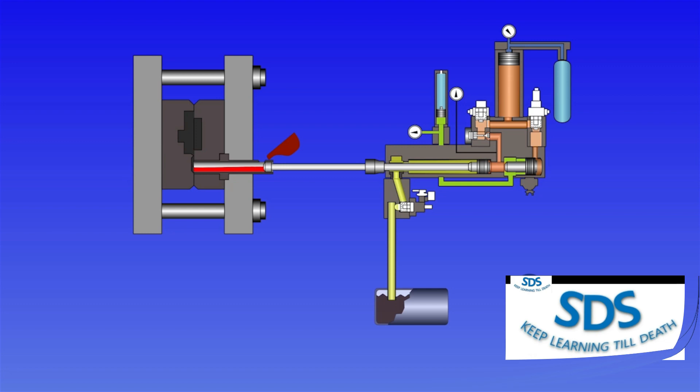The first phase of injection is used to eliminate the gas from the sleeve and prepare the liquid metal for injection into the die cavity. This is a slow movement with a typical velocity of around 0.5 meters per second.